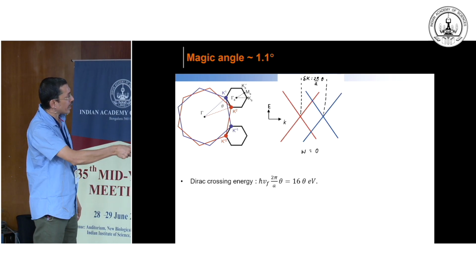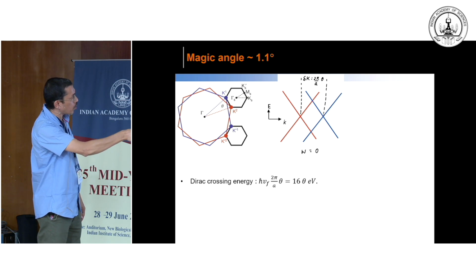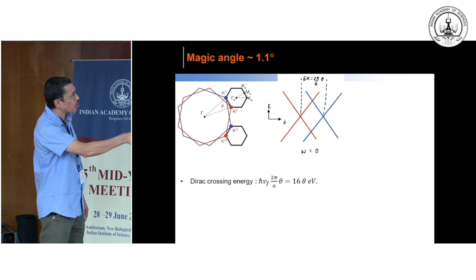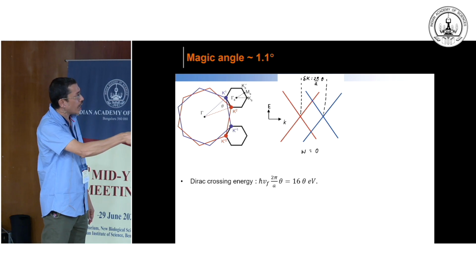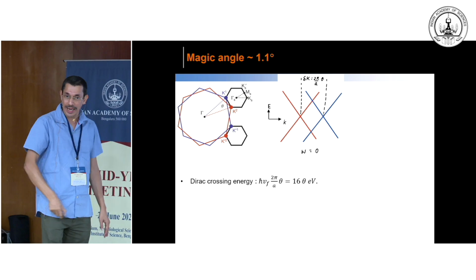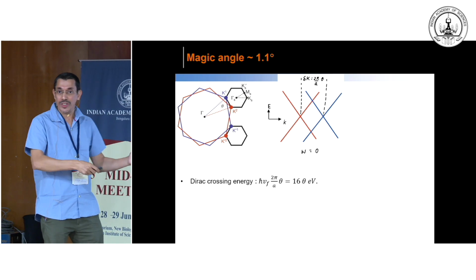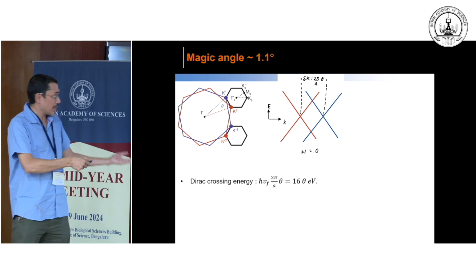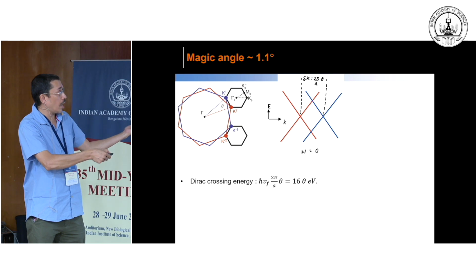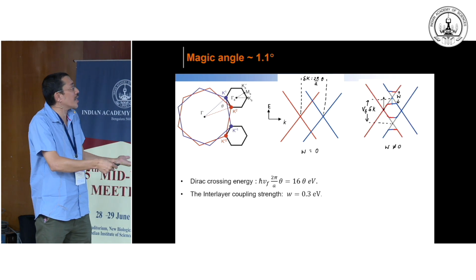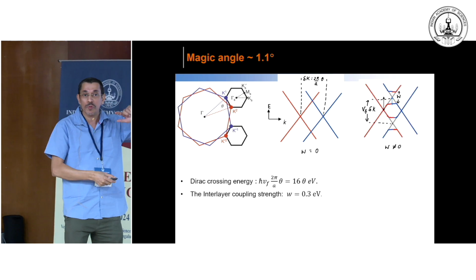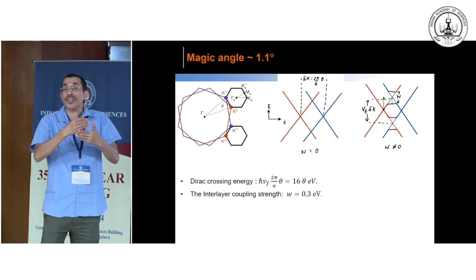If you look at the energy dispersion of, let's say, the bottom graphene and top graphene, these 2 graphene dispersions might have a crossing point at a particular energy, and that depends on your twist angle. Now, if they don't talk to each other, meaning there is no hopping, this will be the band structure of the system. But in reality, we know that electrons hop between the top and bottom layer, or in other words, they are talking to each other.